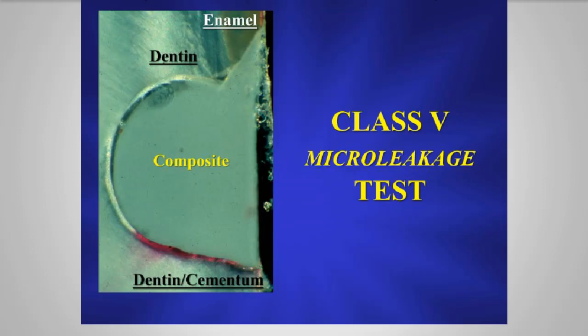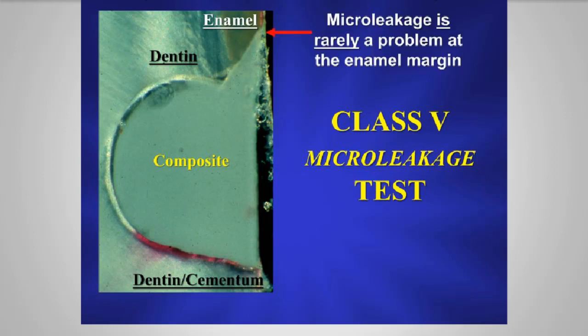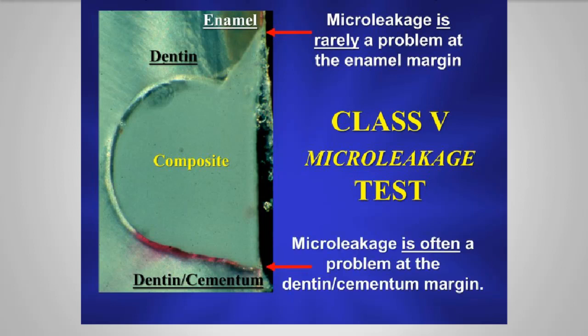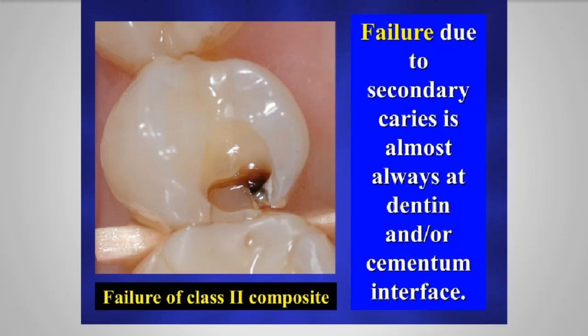And you can do a classic class 5 cavity micro-leakage test as you see depicted here, and no matter what adhesive you use, very rarely is micro-leakage a problem at the enamel margin. Very often, though, no matter what you use, you see a lot of leakage at this dentin and/or cementum margin. So this is a margin that we need to manage. And I'm sure all of you listening to this presentation see what I see clinically. When these composites fail, where do they fail? They fail very often in class 2s down in these deep box areas. Again, typically where you have cementum and/or dentin. That's where they seem to fail. That's where they leak. That's where they fail. So I think it's those interfaces that we need to be most concerned with.